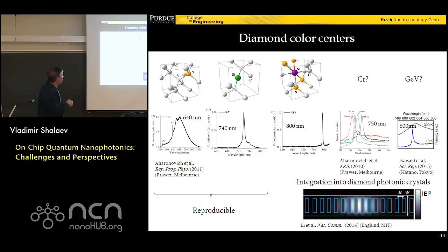And the reason why in nitrogen vacancy it's broad and in silicon it's narrow is that the nitrogen vacancy doesn't have a center of symmetry. Therefore, it is very sensitive to local position. Since local electrical fields are different in different positions, you could have all this shift in the photoluminescence, the so-called spectral shift. Whereas silicon does have a center of symmetry, and as a result it's not sensitive to these fluctuations in the local electrical field. So one way or another, the line is much narrower.